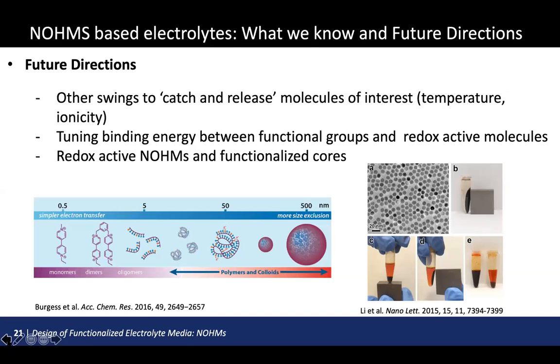Well, that's classical diffusion, but if you can engineer a hopping mechanism, right? There's something called a Grotthuss mechanism for protons anyway in ionomers, for example. Essentially the proton just hops from site to site while the sites more or less don't move very much. They wiggle a little bit. I don't know if it's possible to do that with, let's say, copper ions or something like that.